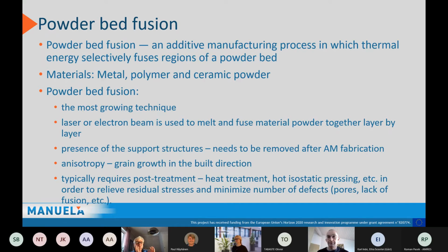We need a lot of support structures which need to be removed after the fabrication. We may get different properties in different directions since it's a directed build. Typically, in normal cases, there is some kind of need for post-treatment, heat treatment, in some cases what we call hot isostatic pressing, etc., to relieve residual stresses or perhaps for defect control. But this must be known. These are the ones we talk about, but still this is the growing technology.